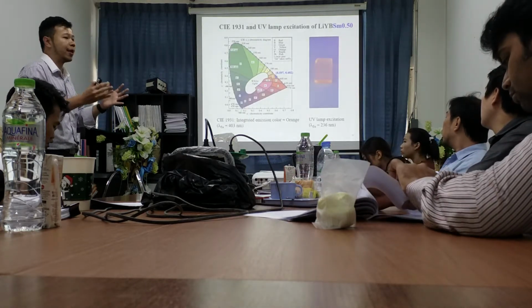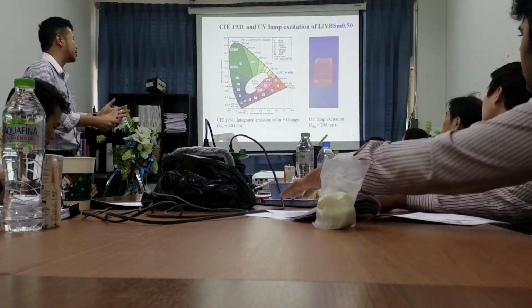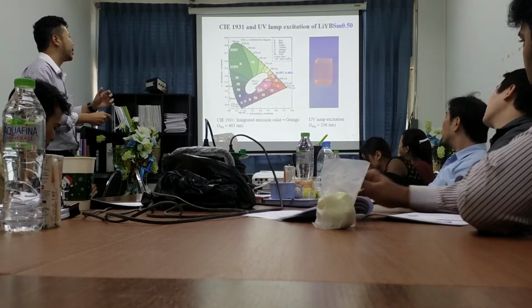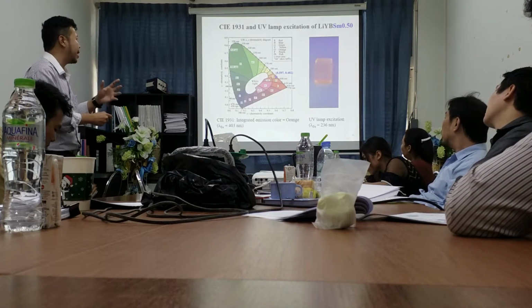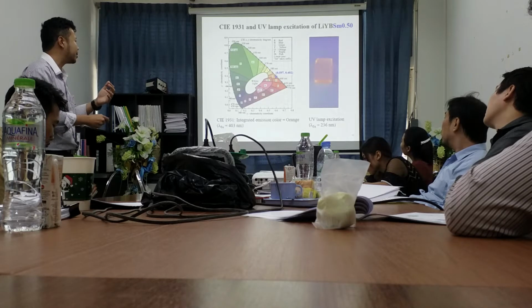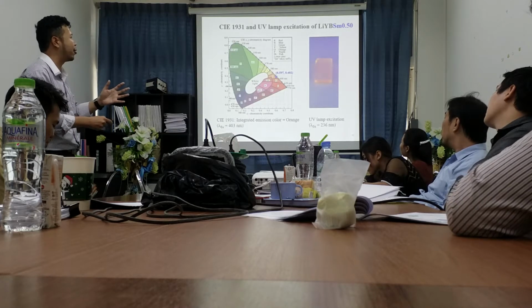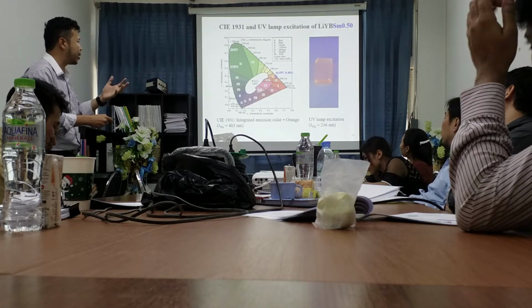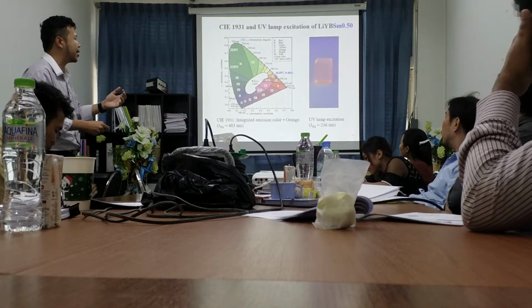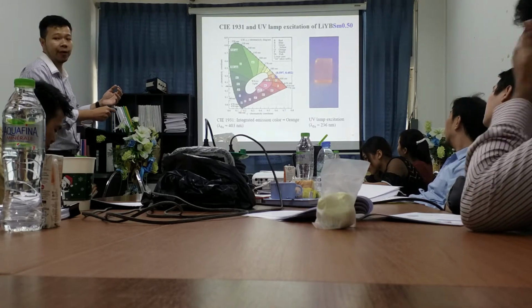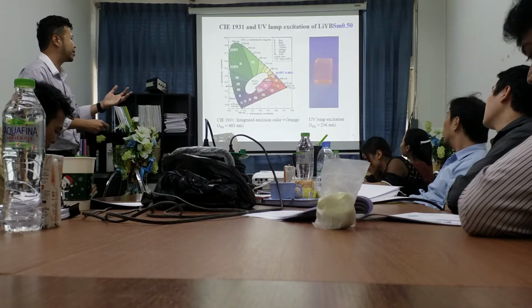I took the emission spectra for color coordinate evaluation, and the color coordinate is in the orange region. That means in theory, this glass performs orange emission, and I confirmed it with an actual picture under UV lamp excitation. It shows the exact orange color when we excite it with the UV lamp.